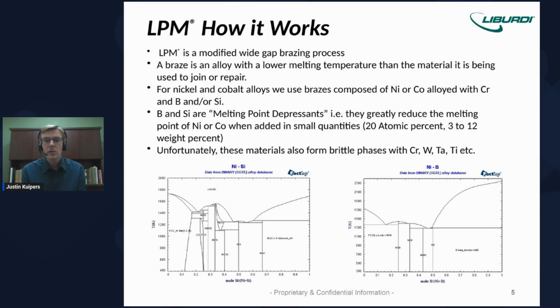For nickel and cobalt alloys, brazes are typically composed of nickel or cobalt alloys. They contain generally chromium and may contain other alloying elements, but in particular, there's generally boron and or silicon that are added to these alloys in order to lower the melting point. So as previously stated, we need an alloy that has a lower melting point. The way that's achieved in nickel and cobalt alloys is by adding boron or silicon, which are termed melting point depressants. So the addition of these elements is useful in that it allows us to create braze alloys with lower melting points, but they also are detrimental, and so we want to only add as little of these melting point depressants as possible.